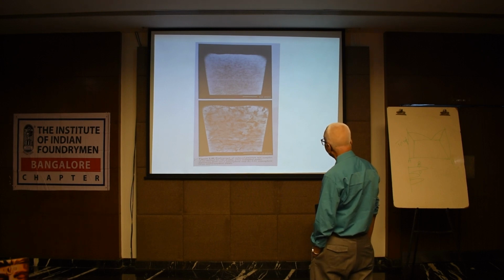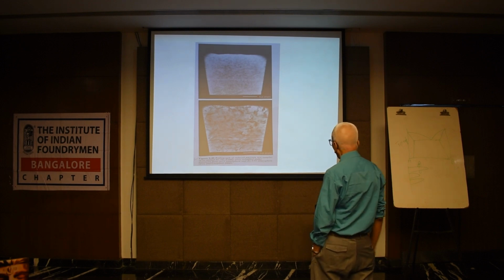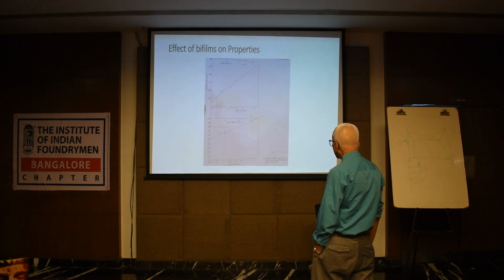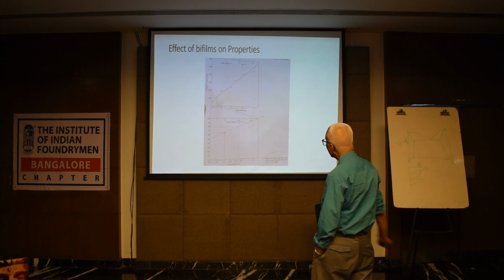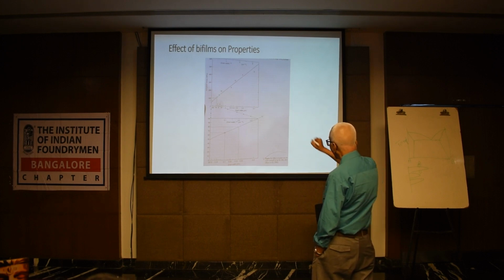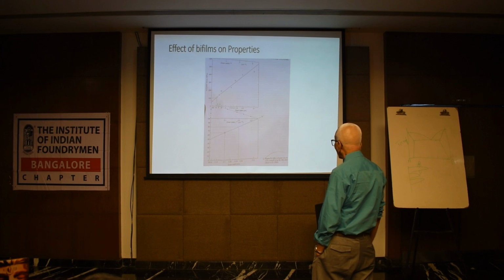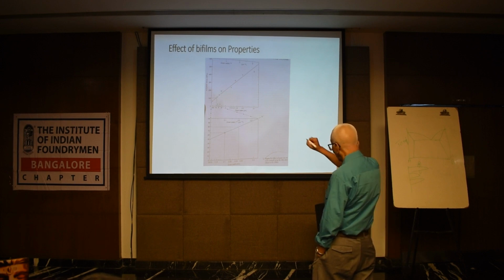And then you can see porosity in the bottom tank. That's due to bifilms. And the top one, less porous. Next slide, please. The effect of bifilm on properties. You can see the proof stress versus grain width, and that goes like that, and it drops down in the schematic. So the proof stress drops with bifilms.